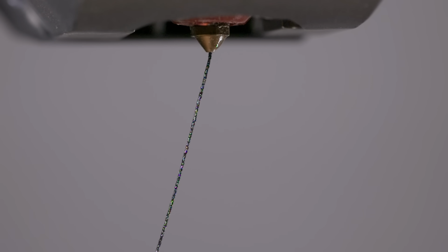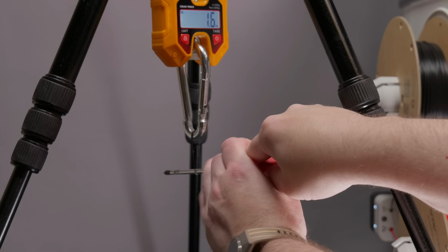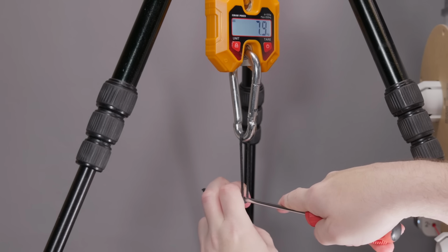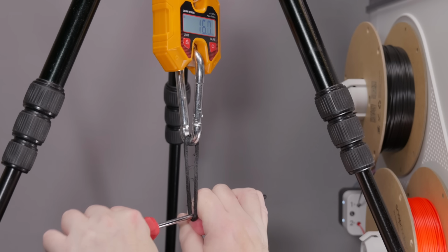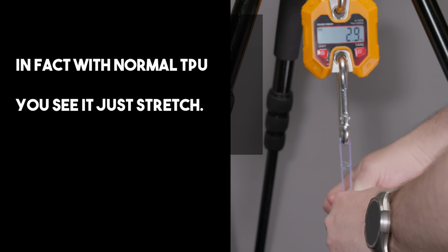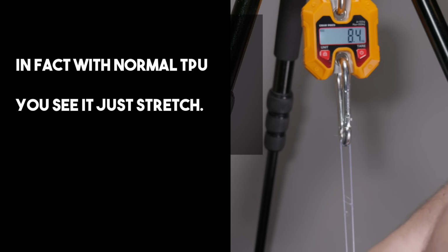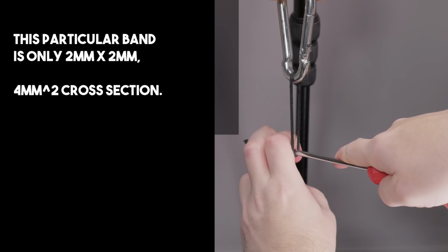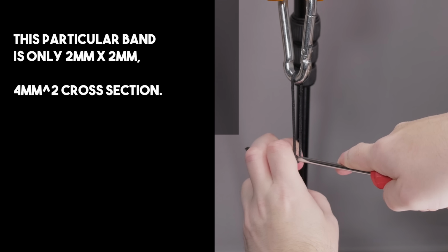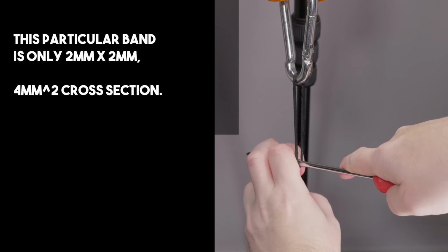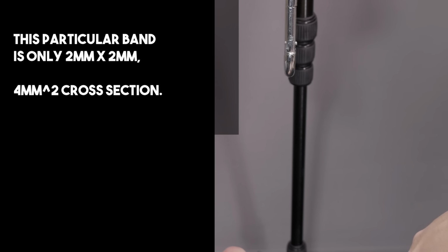The thing is, when it comes to stretching TPU GF, you'd think it would be possible to stretch the TPU in such a way that the plastic will effectively slide off the glass fibers internally, causing a permanent weakening of the material. That does make sense, and yes, that does happen, but not as effectively as you might think, because when you stretch a polymer, the material narrows, so it will grip the fibers up to a point when the material will finally slip, and then the fibers will become permanently ineffective. But of course, this won't happen all at once because it's a sort of chaotic process. In TPU GF, this actually takes more load than you might think, so it's probably only going to happen in situations where you've really pushed the limit too far, and in these cases, you'll be looking at permanent catastrophic failure.